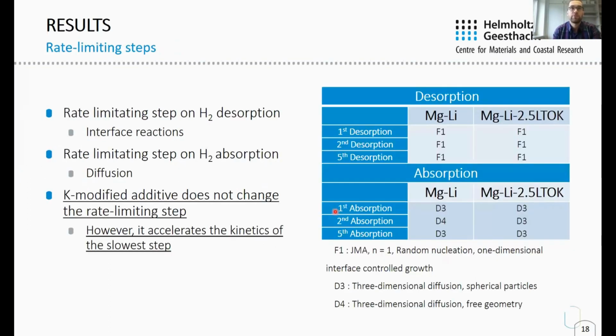In order to further investigate the effects of the additives, an analysis is carried out to determine the rate limiting steps of pristine and potassium samples using a mathematical model called the Jones and Sharp method. The results are summarized in the table. Desorption rates are limited by an interface controlled mechanism, while absorption rates are limited by a diffusion controlled mechanism. The potassium modified additive doesn't change the rate limiting step for the desorption and absorption reactions, but it accelerates this slowest step of the reaction in both cases.